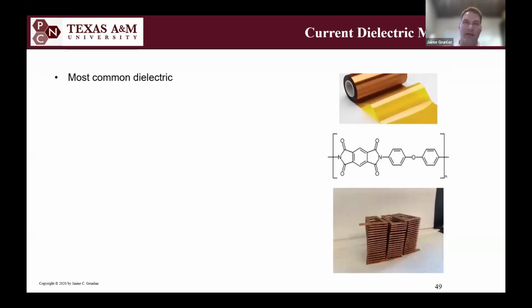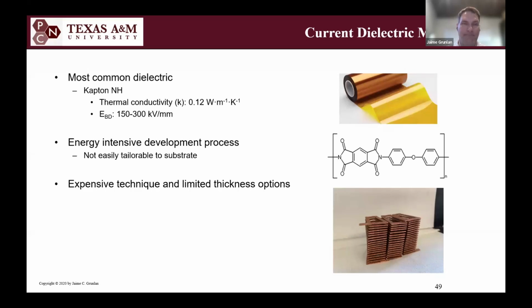And so my competition, the commercial most commonly used dielectric, is Kapton, or some variation of it. I know there's a bunch of different versions of Kapton. But I think the breakdown strength ranges between 150 and 300 kilovolt per millimeter. Thermal conductivity, you would like thermal conductivity to be as high as possible. Most polymers have very low thermal conductivity, as does Kapton at 0.12 watt per meter Kelvin. And so there's a desire.